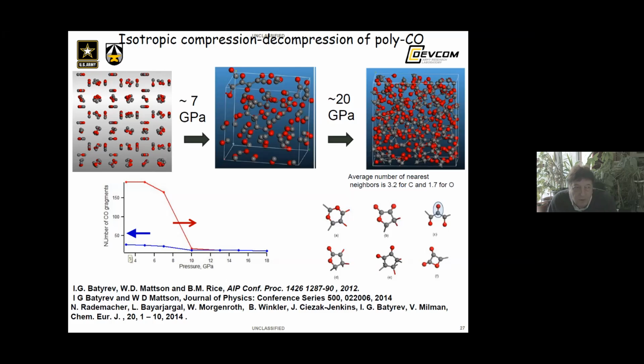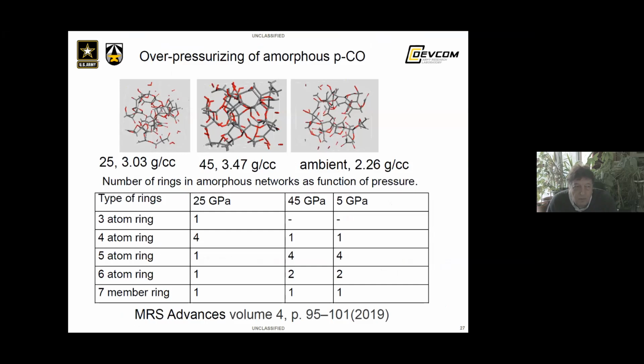What happens if we compress the random network further? Pressure removes small atom rings, accumulating significant strain. After the release of the pressure down to 5 GPa, the high pressure ring structure remains the same. So it can be seen from this table. Mass density is changing from 3.03 gram per cubic centimeter at 25 GPa to 3.47 at 45 GPa and down to 2.26 gram per cubic centimeter at 5 GPa due to an increase of the interstitial volume, while most of the covalent rings in the amorphous network are sustained.